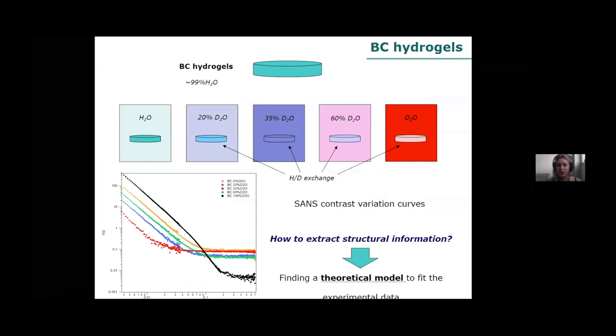Going back to scattering length densities, very important for planning experiments: we find contrast between crystalline and amorphous cellulose when using X-rays. In the case of neutrons, we can generate contrast between cellulose and different degrees of H/D exchange by soaking the pellicles in D2O mixtures, or by producing fully deuterated cellulose. The approach we followed was to soak the hydrogels in different mixtures of D2O and water, and we also tested partially deuterated cellulose by feeding the bacteria with deuterated glucose.